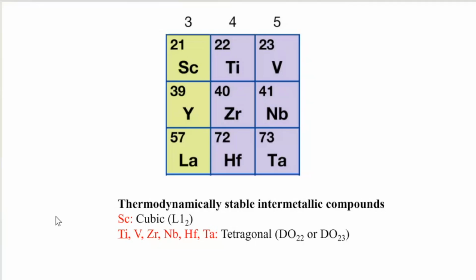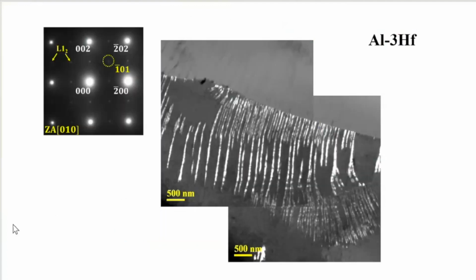So we decided that let us look at these elements and see what we can do. We started with zirconium and hafnium. But one of the first problems we encountered is that if you add hafnium to aluminum, it produces a cellular precipitate. This is one of the microstructures we obtained, which I like very much. It shows the cellular precipitation from a grain boundary, and also the coarsening of those cellular precipitates. And we all know the moment precipitates of this morphology appear, the strength goes to a very low value because it fractures at the boundaries.